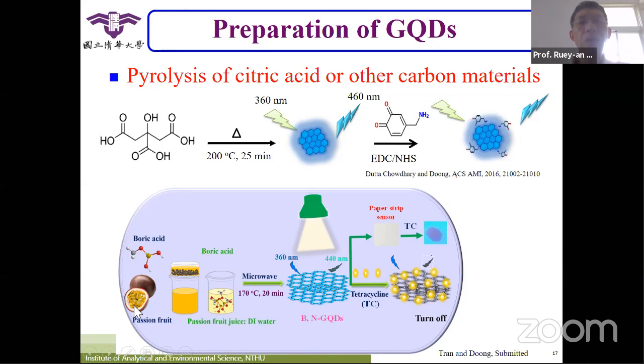So that's, for example, in my lab, I just used passion fruits and put some boric acid in. We get rid of the seeds of the passion fruit, have their juice here, and put the boric acid inside. Still use the microwave, 170, 20 minutes, and then we can get the graphene quantum dots. If you add the boric acid, you can get the boron-doped graphene quantum dots.